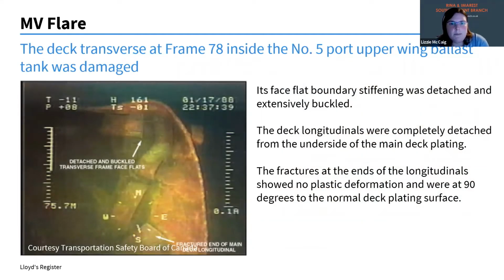So what happened here was that they found that the deck transverse at frame 78 inside the number 5 port upper wing ballast tank had been damaged. The face flat boundary stiffening was detached and extensively buckled. They found the deck longitudinals completely detached from the underside of the main deck plating. And crucially, the fractures at the end of these longitudinals showed no plastic deformation and were at 90 degrees to the normal deck plating surface. So I think you can definitely see the buckling. You can just about see the brittle fracture, but there's more pictures to come.